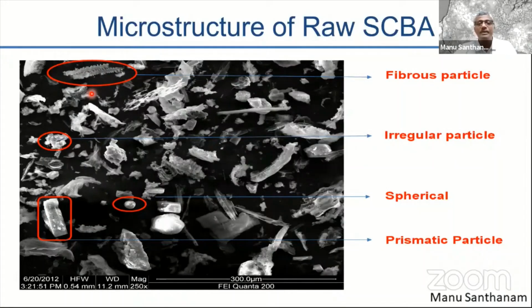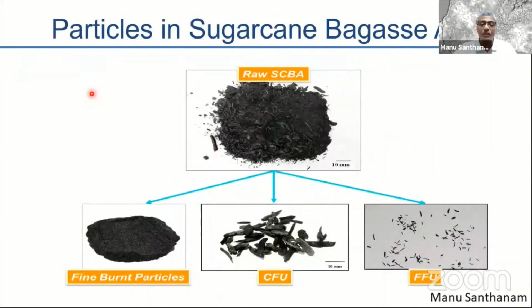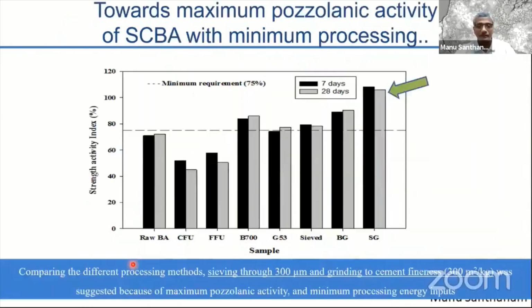So we need to develop a technique that can effectively get rid of this carbon and maximize the amount of silica that we have. So we looked at the composition here. So you could see that there are coarse fibrous particles and fine fibrous particles that are impurities in this otherwise very nicely fine burnt siliceous material. So what we did was we undertook a large scale of processing studies, either grinding it or heating it or sieving it and then grinding it, and a combination of these several studies. And what we found was the best pozzolanic activity was achieved by the material that was sieved through 300 micron sieve that removed effectively most of the carbon bearing materials and then ground to a fineness of cement.